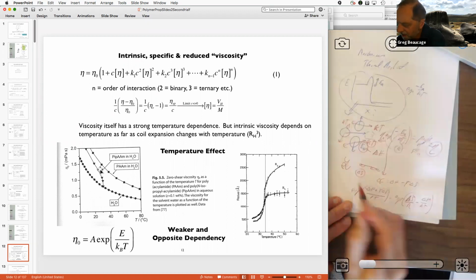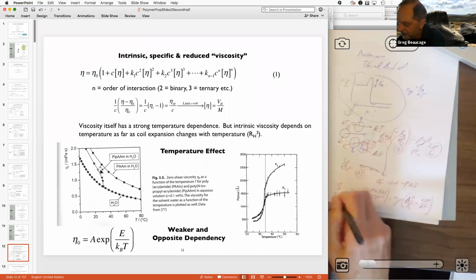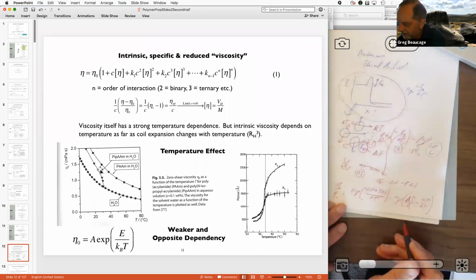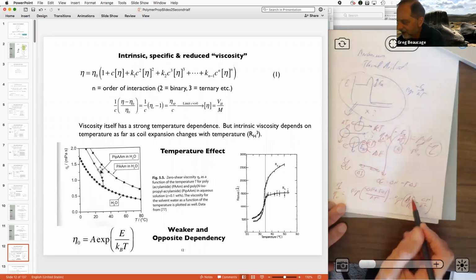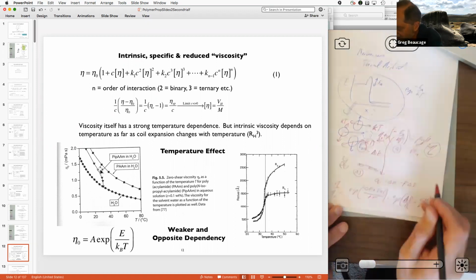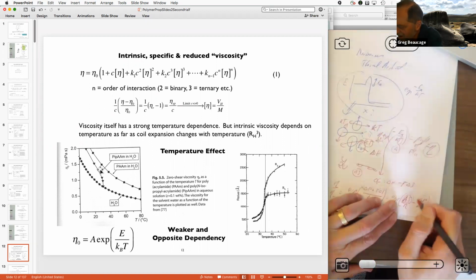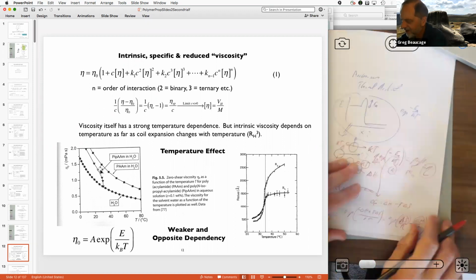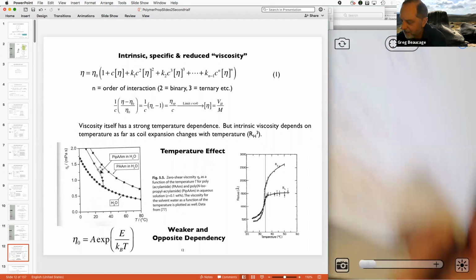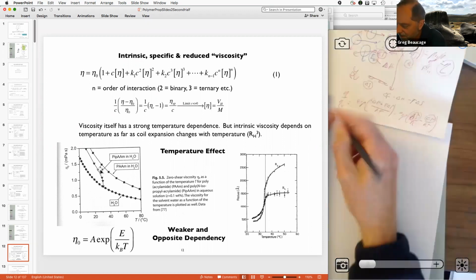This delta S would be like, how does the chain straighten out when it flows? Because you're talking about the viscosity here. So the structure can change, or maybe it had to do with water association with it. Could be a lot of different organizational things with this delta S. So that gives you two parameters for viscosity temperature dependence. There's another twist to that called the Vogel temperature.